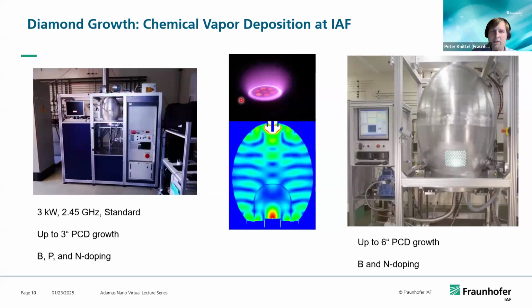And we have two types. One is for smaller area, up to 3-inch polycrystalline growth. We can obviously also grow single crystalline, but there are no 3-inch wafers available at that size. And larger machines can grow on an area of up to 6-inch. The machines are equipped with boron precursors, trimethylboron mainly, phosphine for phosphorus doping, and nitrogen for n-type doping.